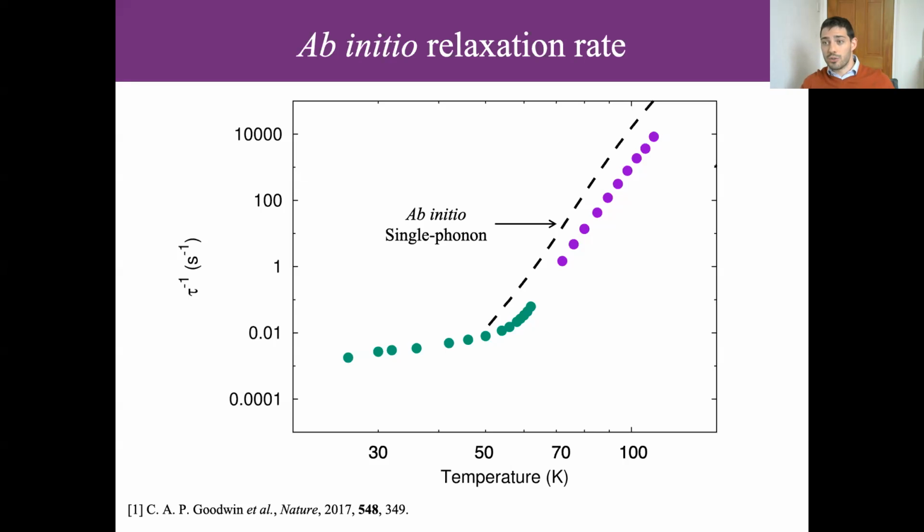This gives rise to not only the width of the peaks, so for instance, not in IR, in INS, this contributes to the width of the peaks, but it also is obviously very important for relaxation. So considering phonon dispersion across reciprocal space, so not just gamma point phonons, right, across everywhere, means there's a lot of stuff to do.